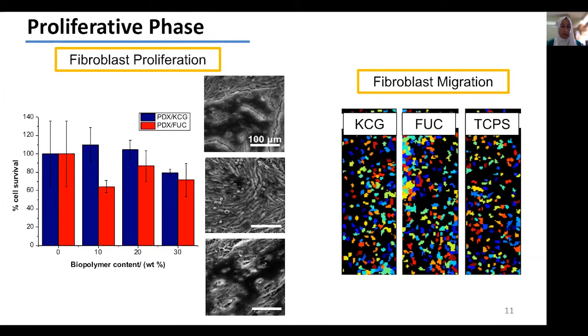Another aspect which is very important in the proliferative phase is the migration of cells so as to close the wound. We therefore carried out in vitro wound scratch assay to look at the migration potential of fibroblasts using the seaweed-derived scaffolds. And the image on the right-hand side basically shows how the wound was closing and how the cells were migrating into the in vitro wound site.